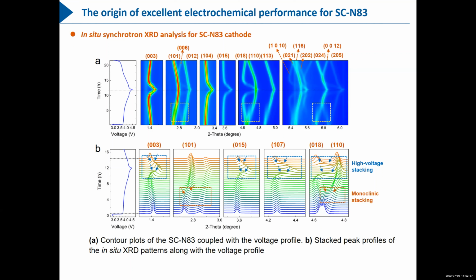We know that this material initially has a hexagonal structure, right? But when the lithium ions get out of the structure, we find a phase transition has been observed. This is a monoclinic stacking. That means there is a phase transition here. Another difference is that at high voltage, the high voltage stacking is very, very complicated, much more complicated than in the polycrystalline structure.